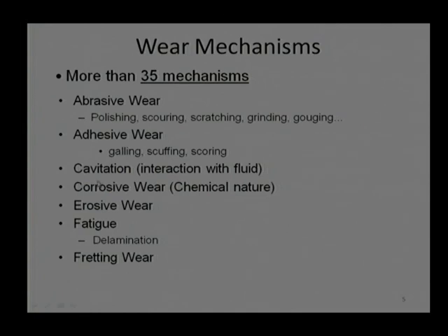When we talk about cavitation, basically we are talking about solid versus liquid. It is something like bubbles getting burst, and because of the bursting of the bubbles, there will be excessive pressure, which will be directly impinging liquid with a high velocity on the surface, and that will cause some failure, which is known as cavitation failure.